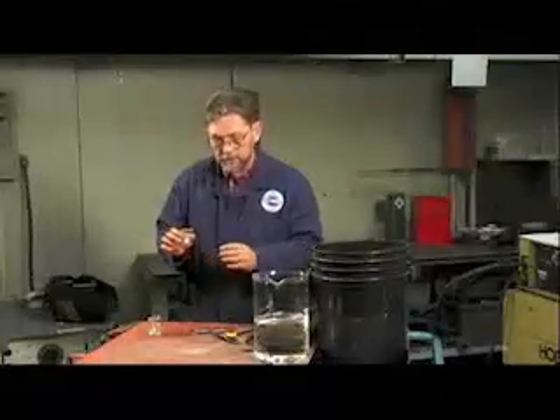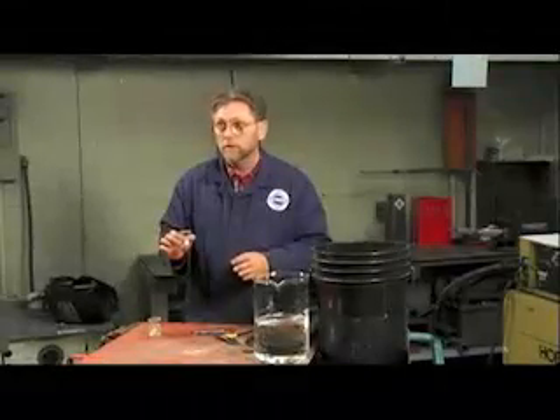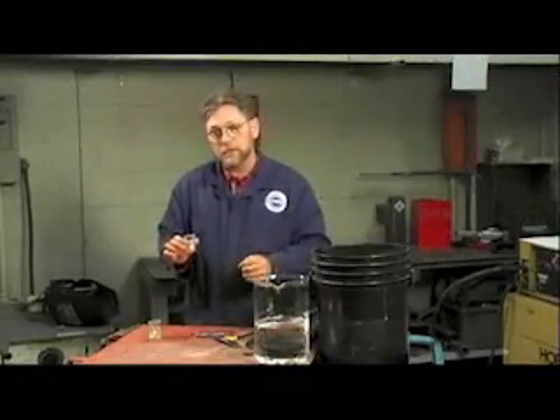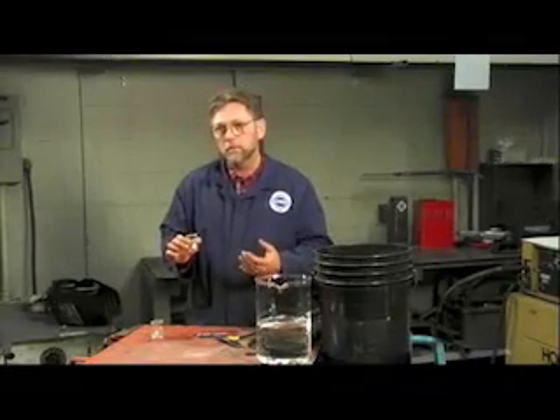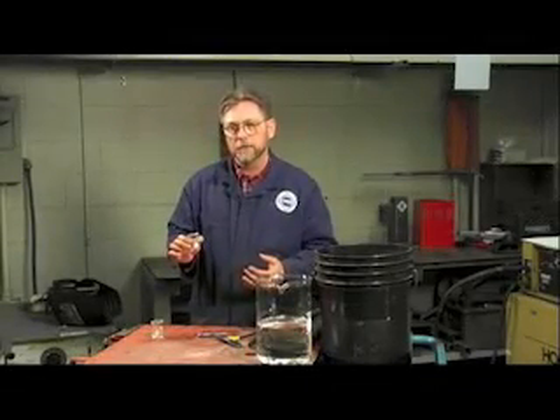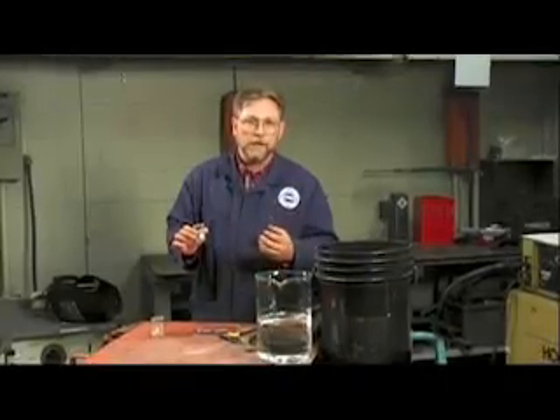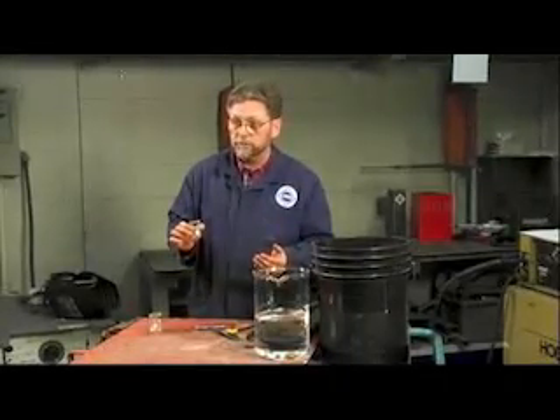If we then change processes to gas metal arc welding, we'll find that because we're not using a flux now, we use a dry, clean solid wire electrode and a dry gas, so that there's very little source of potential hydrogen, the amount of hydrogen that would actually be absorbed will be quite small. In fact, perhaps only a very small amount, and will even be dependent upon the humidity in the welding shop that day. But the difference is that it is quite low.